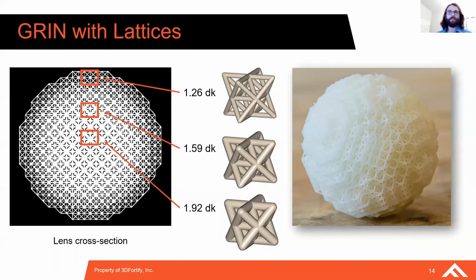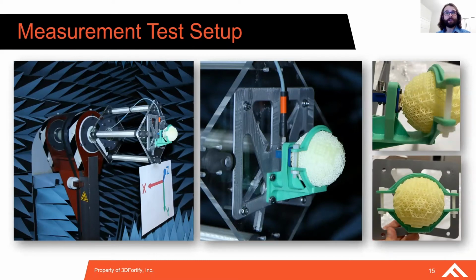The GRIN lens on the right was printed at Fortify on a Flux Core printer. We then took this lens and mounted it to a fixture in front of an open-ended waveguide feed source, which was then affixed to the test rig in an anechoic chamber. The lens was illuminated at 25 to 32 gigahertz, and the beam patterns were measured.